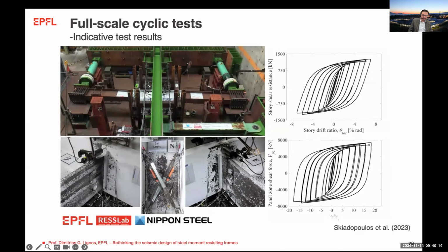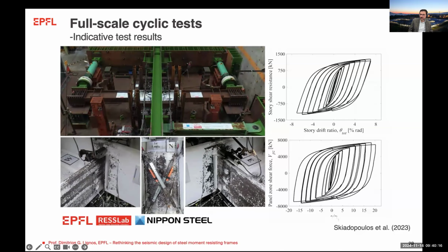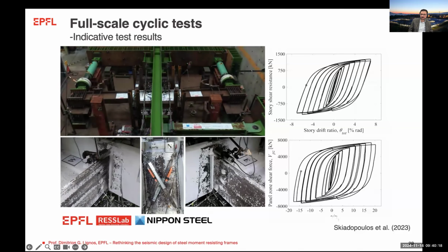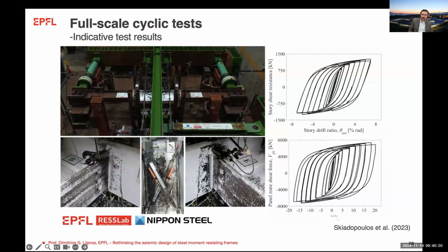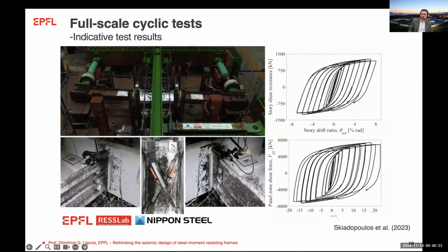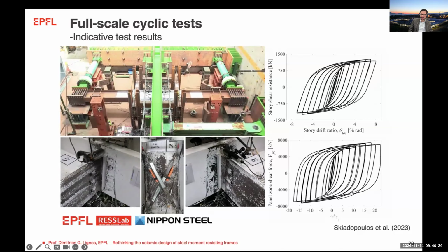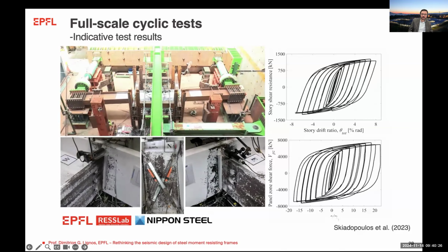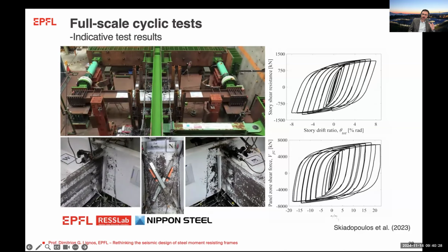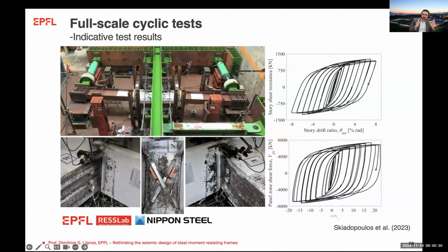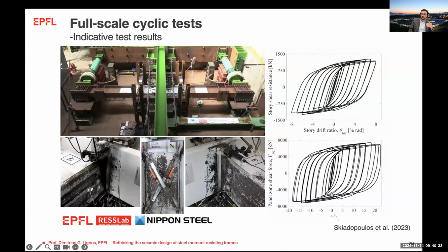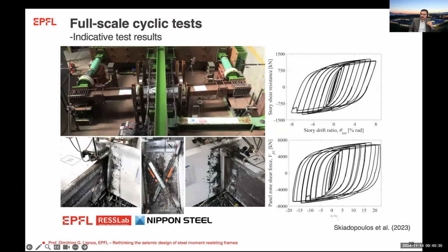So basically here, we kept testing this, and the ultimate failure mode in this case would be ultra low cycle fatigue, but that would only happen at drift levels that are well above the maximum considered earthquake and would be in a range where the system is not going to be governed by degradation, but the system behavior is going to be governed by P-delta effects. So that would mean that degradation is not going to influence system behavior.